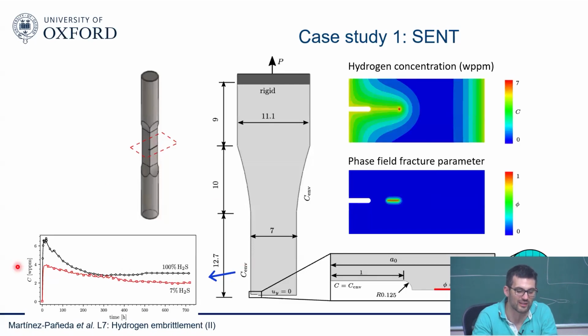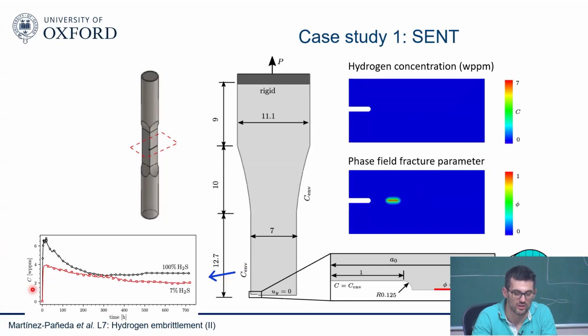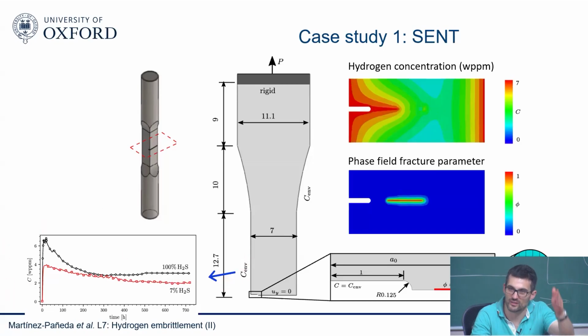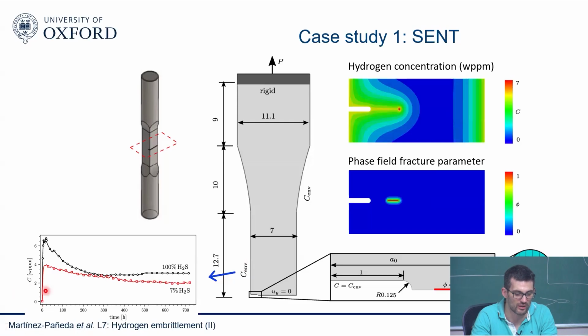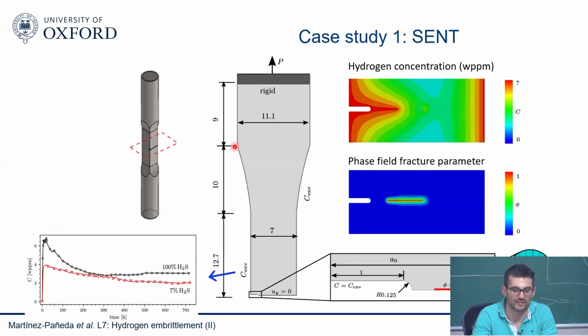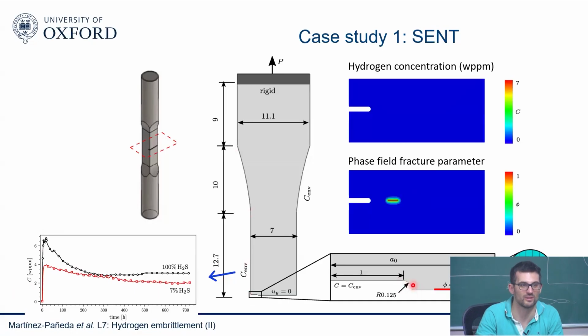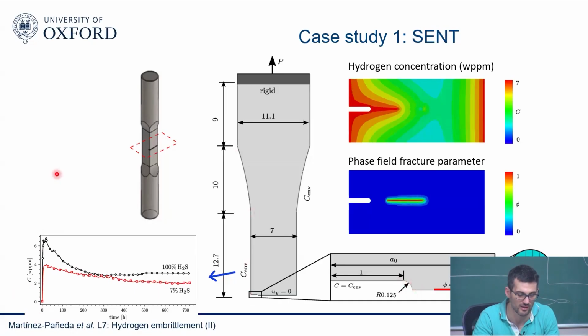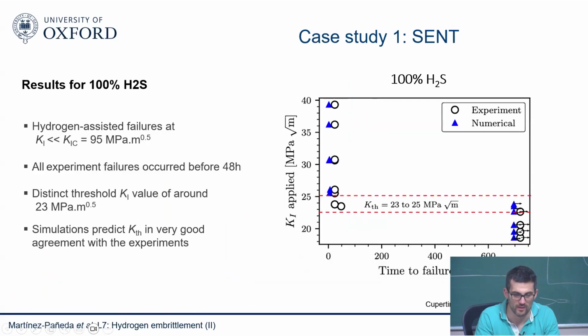you can see that clearly one aspect to improve is this one, because this is what we see on the permeation test. When we have a clean surface, we expose the material to hydrogen and it goes down. And this is probably fine for here. Whether this applies here, I don't know. It's an approximation of what happens ahead of a crack. But anyway, this is the boundary condition. And this is what we saw, basically.